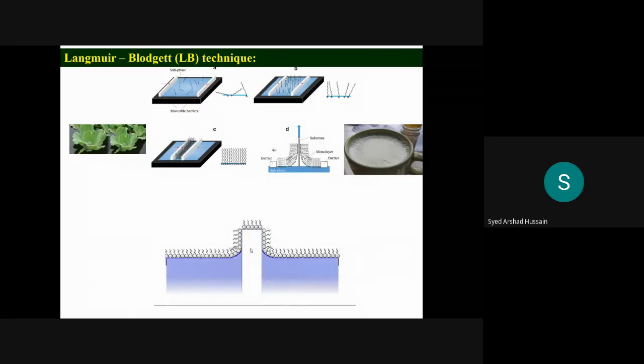And this deposition process is like, we have all seen the cream when milk is heated; you see a cream layer formed. And if you dip a spoon and take it out, you will see cream attached to the surface of the spoon. The same thing happens here. But the main issue one has to remember is that it is very precise, because you are transferring molecules. And in principle, using this technique, one can prepare a layer of the order of one molecule thick. You know, by discovering this technique, Irving Langmuir got the Nobel Prize in 1932.